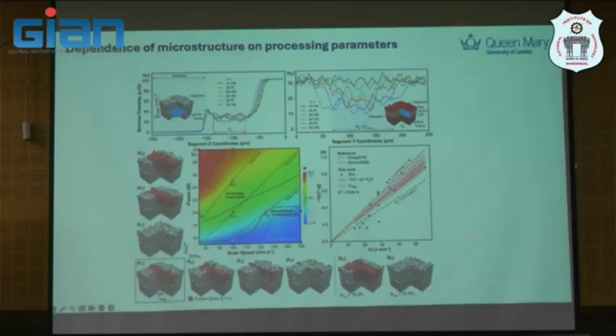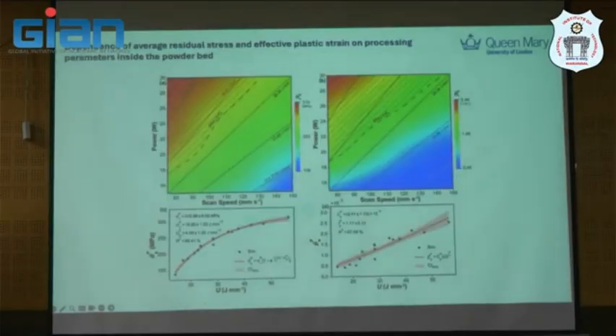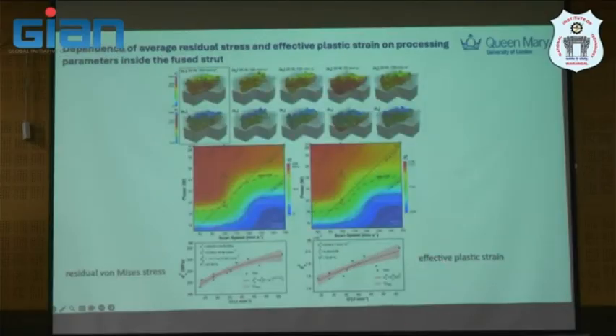And the reference here shows different, how to say, I can't remember exactly, but anyway, this is some comparison with, I think, energy with a plastic strain or something like that. And then you have different PV diagrams at, I think, slightly different conditions here as well, I mean, setup. And that contributes to the prediction of the plastic strain and then the residual stress profile, compared with experimental work as well. And this depends on the processing condition, so you will get different profiles. So quite interesting to look at and understand what happened during the processing of this specific material.